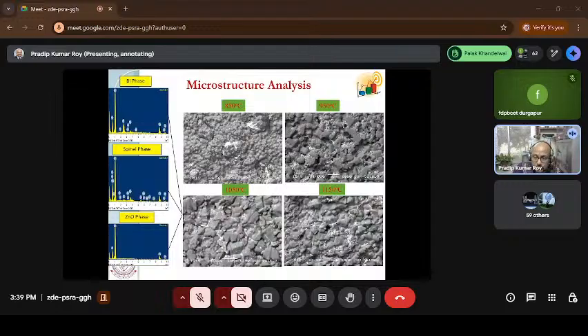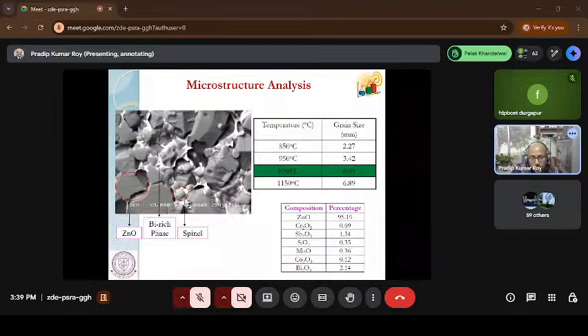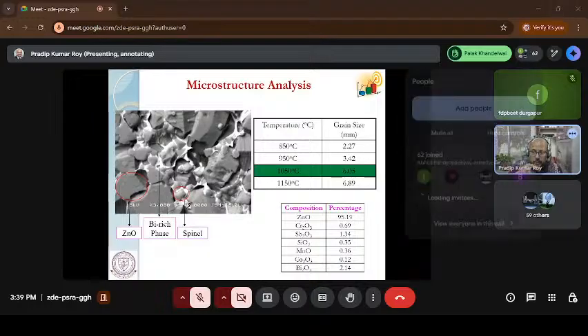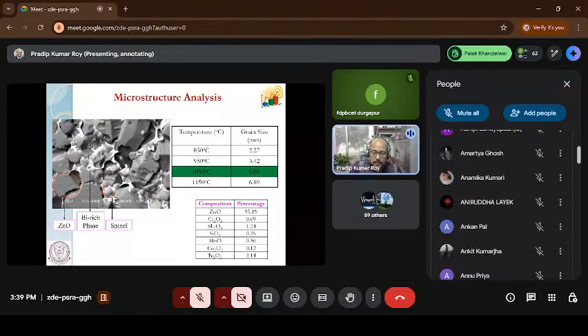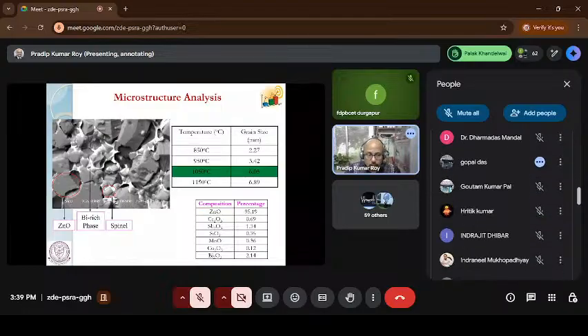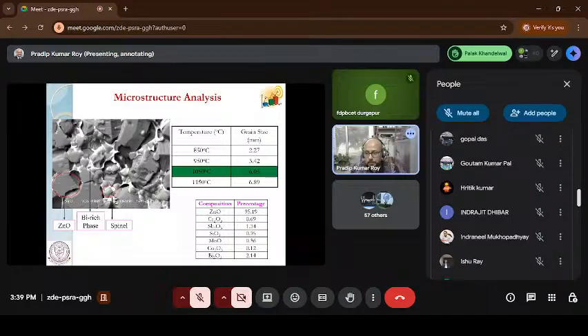Then we see the microstructure. Now if you look at the microstructure very carefully, this black part is basically zinc oxide, the white part is basically bismuth oxide. So the zinc oxide is mostly coated uniformly with the bismuth oxide. This is very much required. I said in my previous slide that all zinc oxide should ideally be coated with bismuth oxide. And at the triple junction, where all three zinc oxide grains meet, the spinel is there. So this part is the spinel, placed in between these three zinc oxide grains. This grain structure should be uniform, then only your electrical property would be uniform.